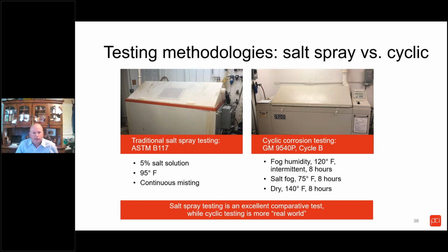The cyclic test—there are multiple tests out there, but I'll take the GM 9540P—is 120 degrees Fahrenheit intermittent fog humidity for 8 hours, salt fog at 75 degrees Fahrenheit for 8 hours, and then a dry period at 140. The idea is that's more real world, where you go through cycles of moisture, heat, and dry, whereas salt spray is just a consistent misting that takes place.